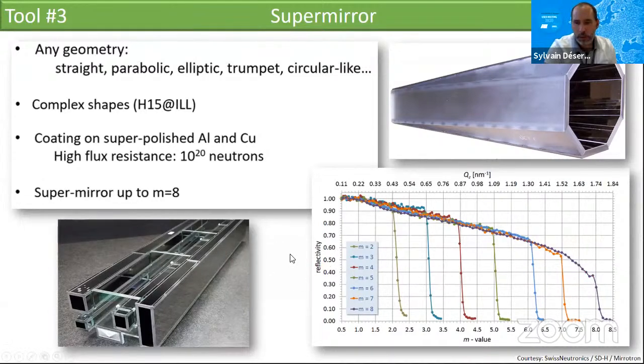It's pretty good, and m equals 8, for those who don't know, means that this multilayer has a critical angle which is 8 times larger than the critical angle of natural nickel. So it means it will be possible to reflect either smaller wavelengths or, for given wavelengths, to reflect larger angles. And this is important when we would like to work with parabolic and elliptic mirrors, for instance.